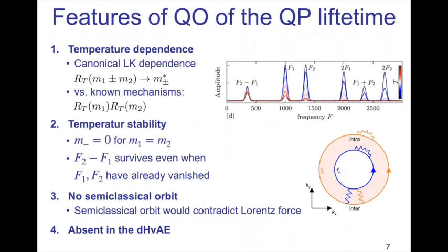The last point, we also computed the de Haas-van Alphen effect, and these difference frequencies are absent in the de Haas-van Alphen effect. You can imagine that simply by the fact that the density of states does not depend as heavily on the quasi-particle lifetime as the conductance or the conductivity.